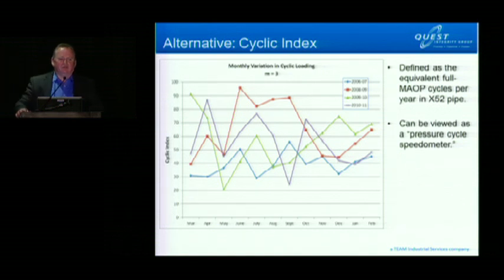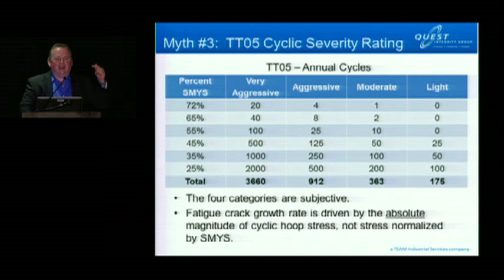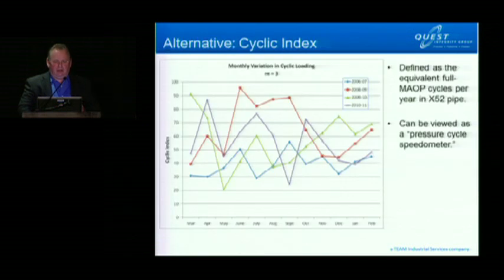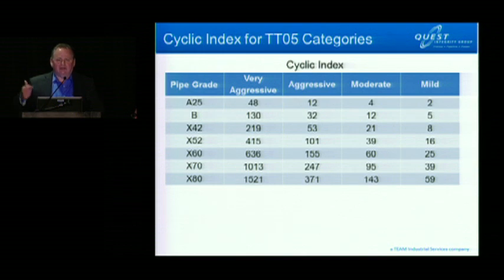This graph shows monthly data over a 4-year period on a particular liquid line. You can see that index kind of bounces around a lot. In one case, it goes from 90 to 20 in a couple of months. And so we think it's a more effective way to quantify how aggressive your cycling is. Now, if I take these numbers and I run them through the calculation of this cyclic index, this is what the cyclic index predicts for the different categories.